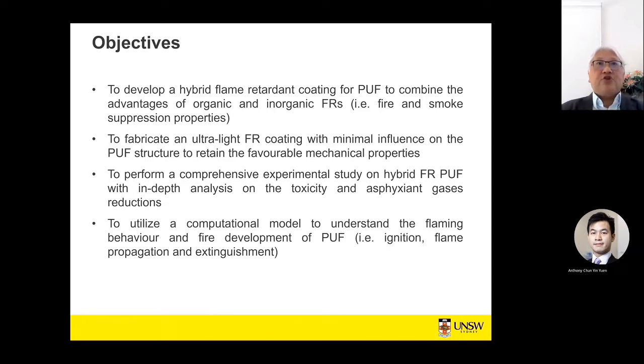And the next step is to make sure that we can apply minimal layers of this hybrid coating so that it has negligible influence on the polyurethane foam structure. In some ways, it still retains the original mechanical properties as well. Based on this development, we rigorously test all these materials on a hybrid PUF. And then we also try to extract some of the data for a computational predictive model.